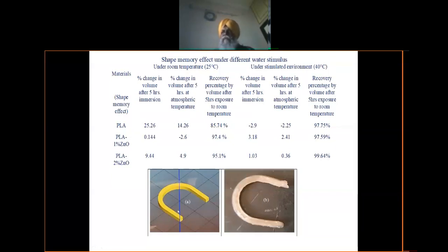Now we want to see what is the effect of stimulus on this particular material. So what we actually did is we selected a stimulus as water, right? So we put the material in water for 5 hours and we see what is the change in the volume. Then what we observed after 5 hours, because most of the materials are hygroscopic in nature, there is normally a rise in the volume. But once you put it again for 5 hours, what will be the change in the volume, whether it is going to take its original shape.